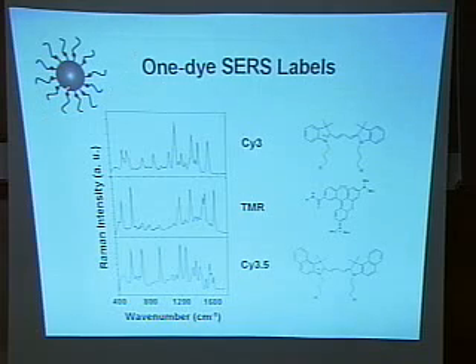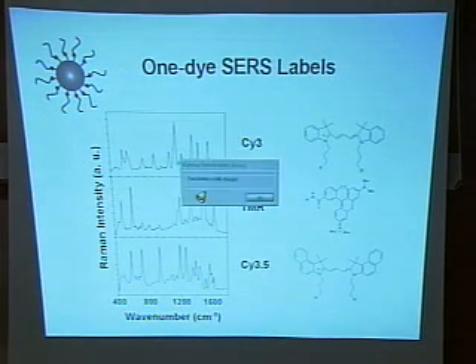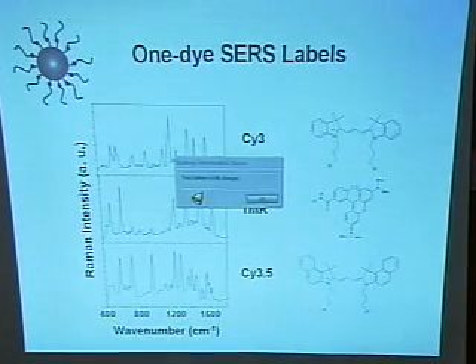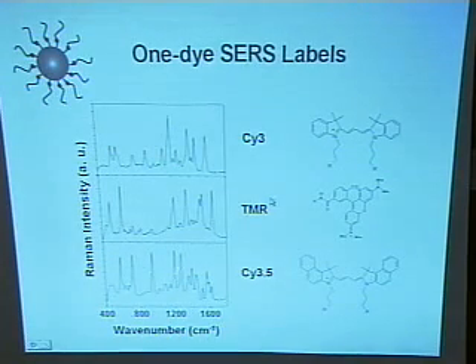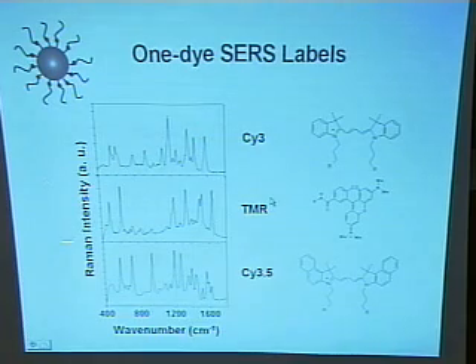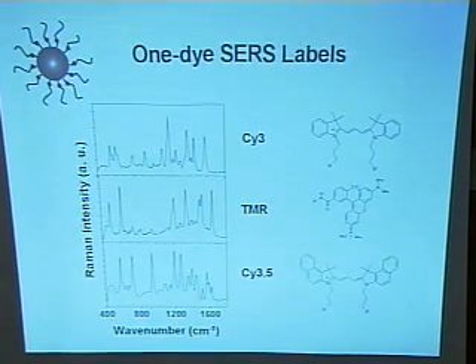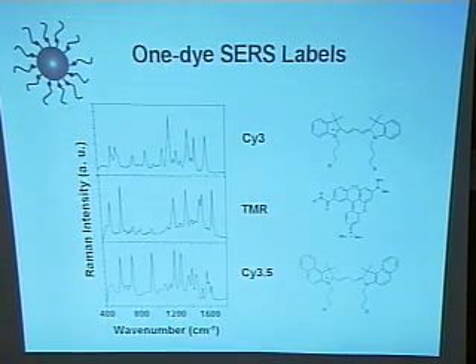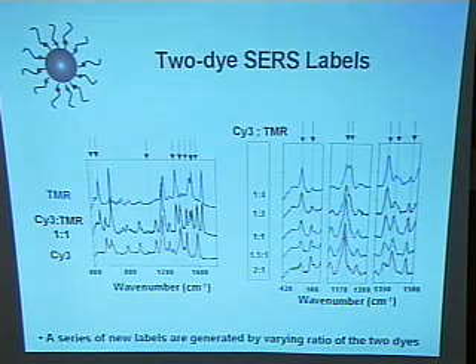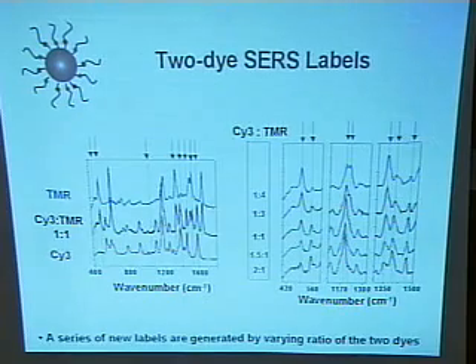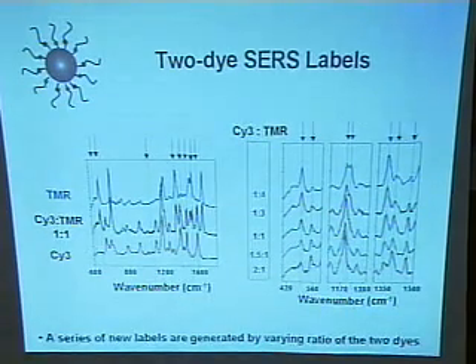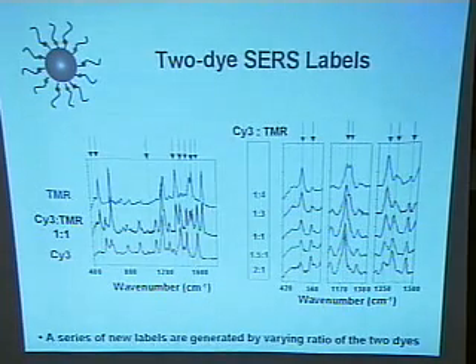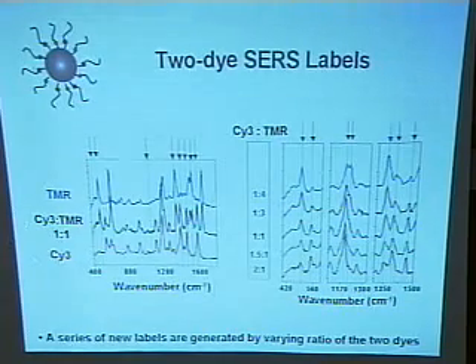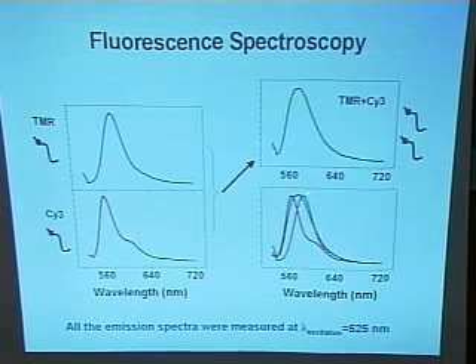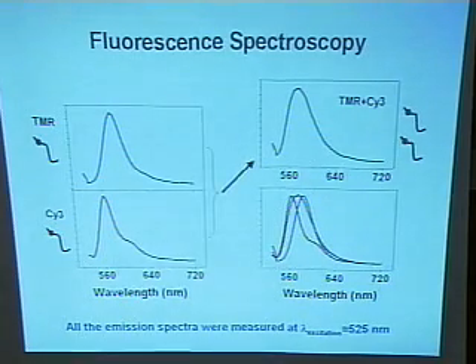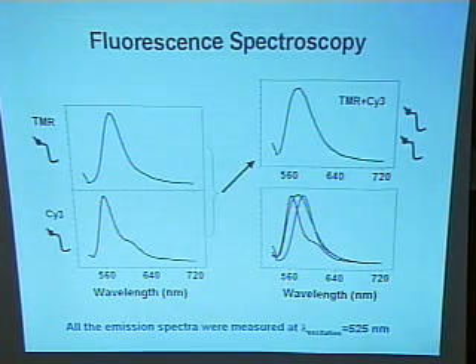One can use one dye label for these different structures. When you change the dyes, you will get different patterns. Then you can use the different Raman spectra to label different probes and get different information about targets. One can also use two dye labels. By varying the ratio of the two dyes, you can generate a bunch of new labels. People will say, oh, you can do this for fluorescent dyes. So I do a fair comparison. I use exactly the same dyes to do fluorescence. This is their spectrum. You can find that if you mix them, it's hard to get even more than one. So this is the power of Raman scattering technology.